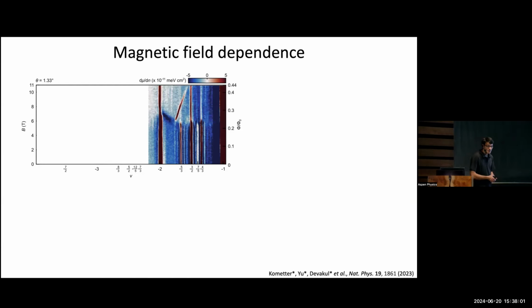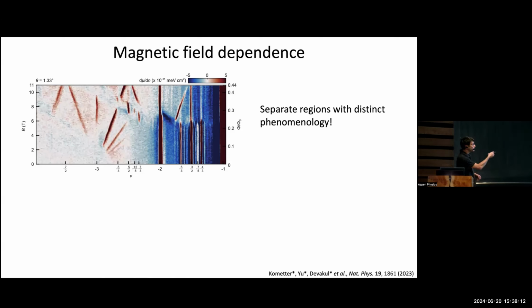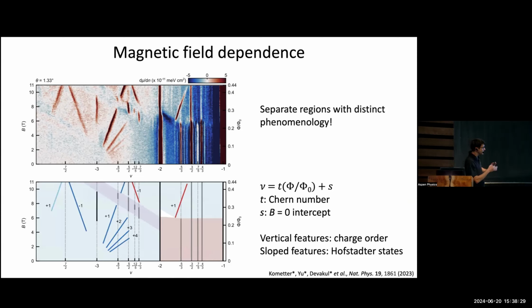Now, something interesting happens when you increase the magnetic field. You can see these generalized Wigner crystal states weaken considerably, and now you start to see something which is sloped. Finally, as you go to even higher density, you can see that actually most of the features that we observe, these incompressible red states, are sloped. There's a small region, I'll come back to this, with vertical features again, but it's a complicated diagram. I'll go through it one by one. Basically, you can see that there is very, very different phenomenology that we observe as a function of this phase space of magnetic field and doping in our system.